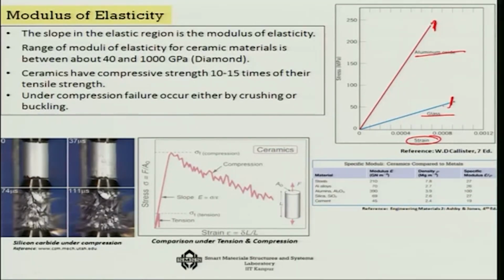And interestingly, if you test them in compression, you would see a failure band happening. So, instead of a single direct failure like in tension, it happens stage by stage in compression. You can see this step by step failure in silicon carbide under compression, and how with respect to time this kind of failure is happening to the system. The take home point is that the elastic modulus is generally quite high, but the failure strain is very low, and the strength is also not very high because of the presence of porosities.